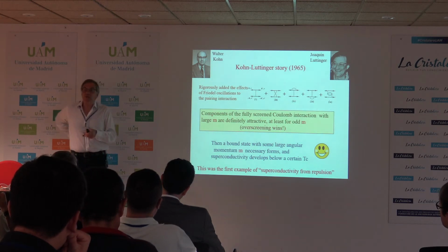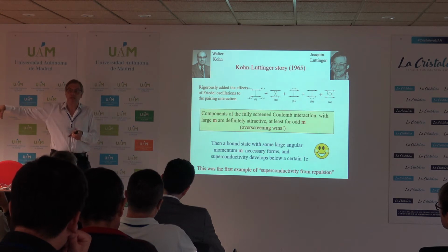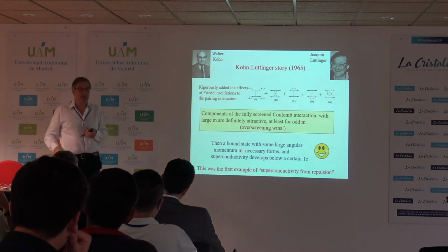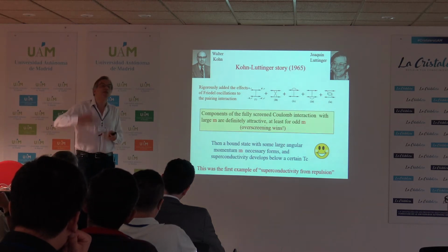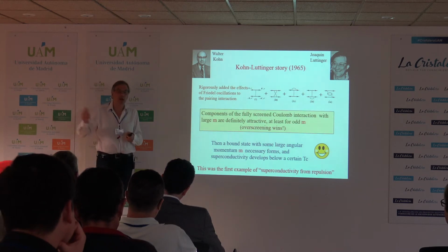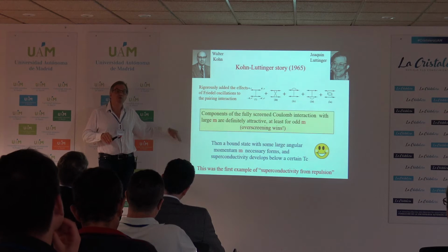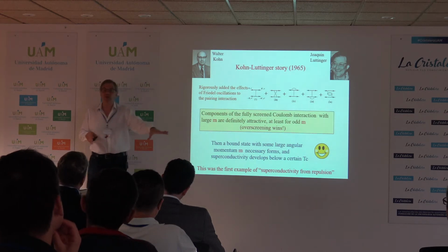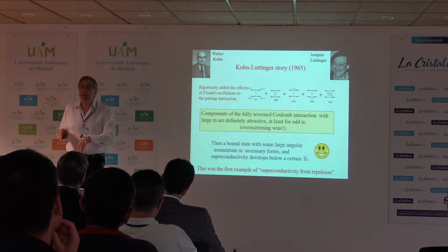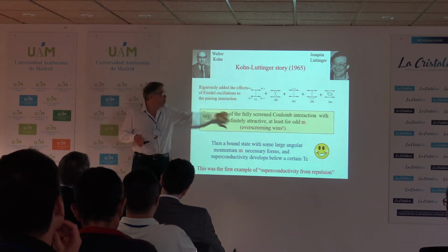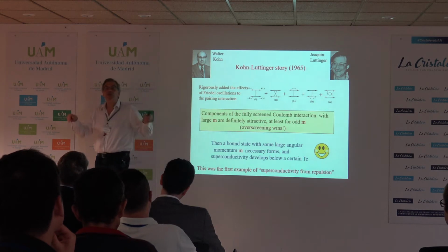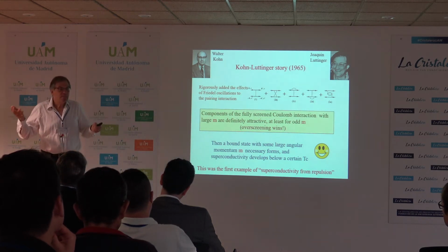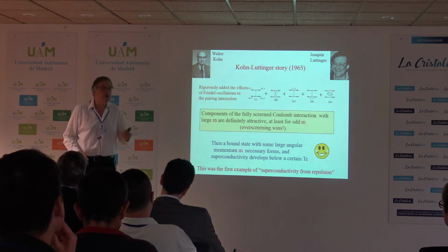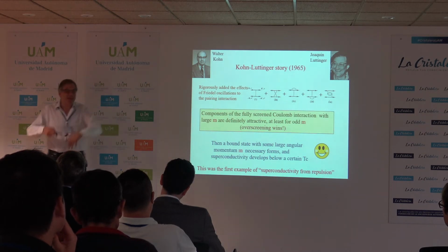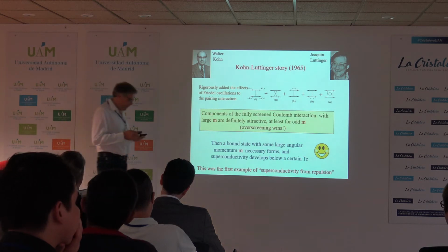Because of non-analyticity, the contribution from this Friedel oscillation decays as 1 over L to the 4th power, which is of course much larger than any exponential function. Then you ask, what is the coefficient in front of this 1 over L to the 4th power? And you find that it only has components u of 0 and u of 2k. Only forward scattering and back scattering, nothing else. And then what they found is that for odd value of m, the coefficient is minus a full square, so it was guaranteed to be positive. For even values of m, it can be positive, can be negative, so there was no theorem.